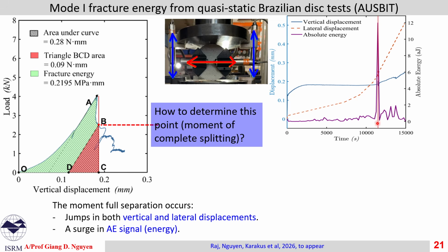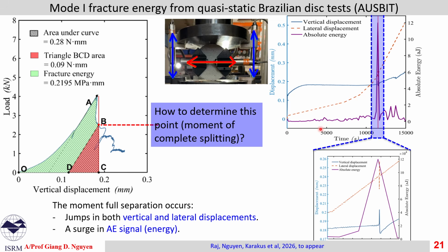The vertical displacement also exhibits something very similar. And this behavior is also confirmed using acoustic emission. At this same moment, or at least roughly the same, they all exhibit a surge or a jump if we plot the AE energy. So once we have identified the moment of complete splitting, we can work out this given point B on the post-peak curve. And from this configuration, as presented earlier, we can work out the fracture energy of the specimen, of the material.